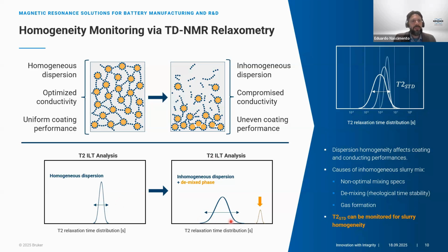And even in the extreme scenario here, you are going to see the appearance of a new peak in this relaxation time distribution graphic. And with this type of information, you can correlate or infer about non-optimal mixing specs. So if you are still in the ramp-up phase, still optimizing the specs of your mixer and so on, but if you are also monitoring the mixing of the slurry, because you produce a slurry in a batch mode, and now you are waiting for the next batch to be coated, so you can analyze to see if this is